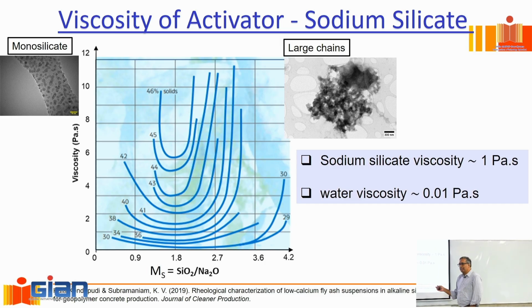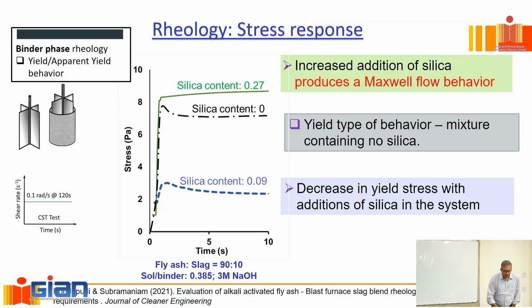How does this compare with cement paste? My water was of a constant viscosity. This didn't change. So I was left to handle whatever came with the cement paste that I could deal with. Here my problem is that depending on the composition, the viscosity of the solution itself will change, and then I have all the other variables that I have to contend with. Right. Now, what is the consequence of this solution?